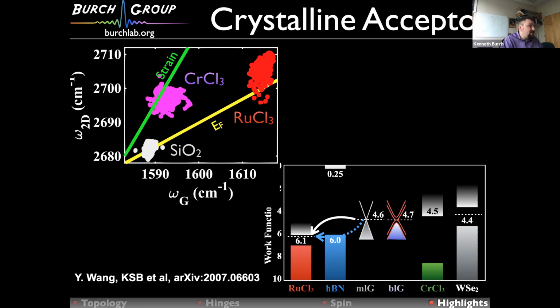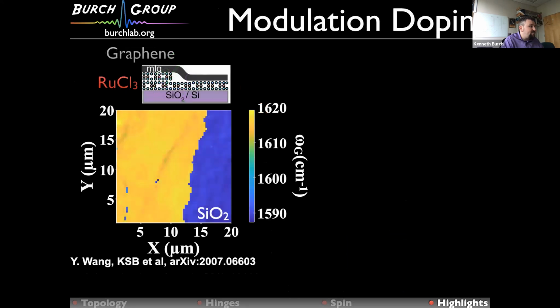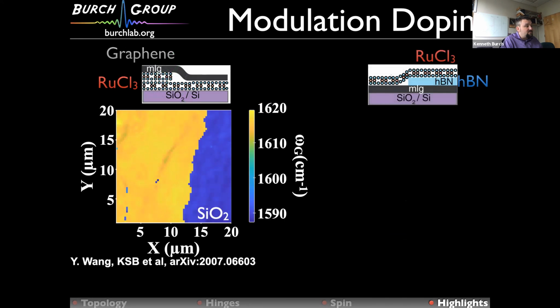And then to check, we made, of course, heterostructures with chrome chloride, and there what we see is a change in the strain axis because of the difference in the lattice constants, but essentially no change along the doping axis. The more exciting thing is, here I'm showing you a map of the G peak, where we put this monolayer graphene over both a single and bilayer ruthenium chloride. From the map, you can easily see where the ruthenium chloride ends, but you cannot tell when you go from 1 to 2 layers, and that's because essentially all the doping happens in a single layer.